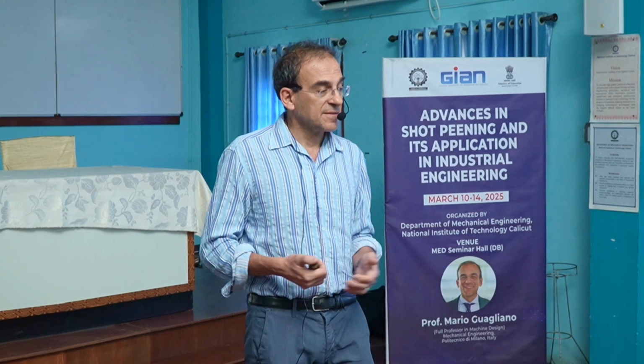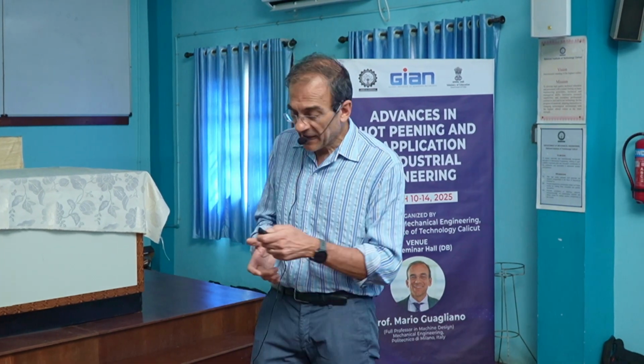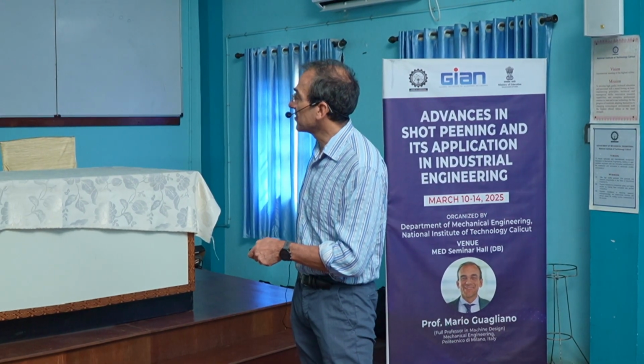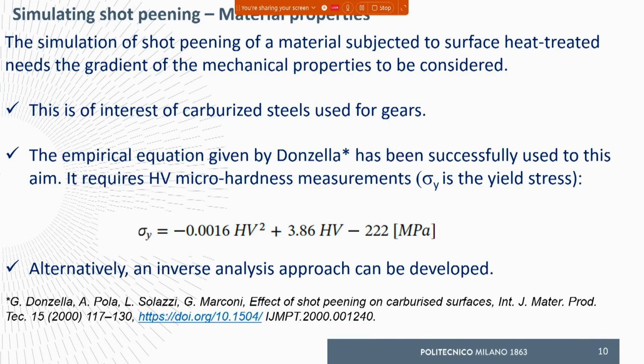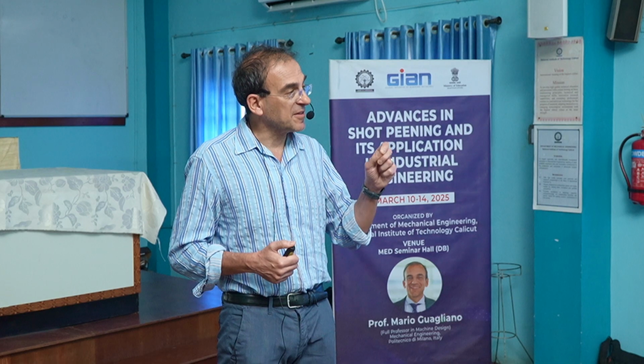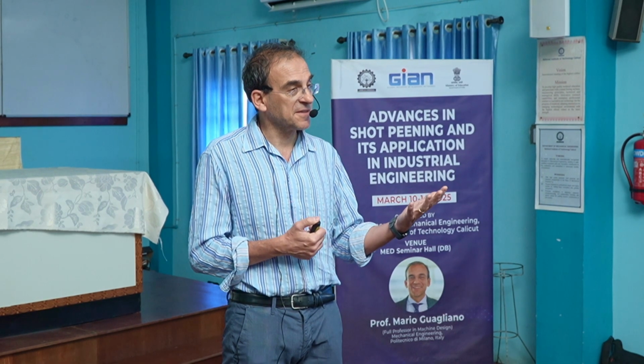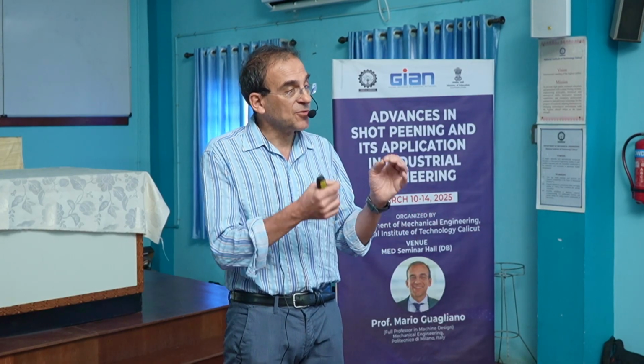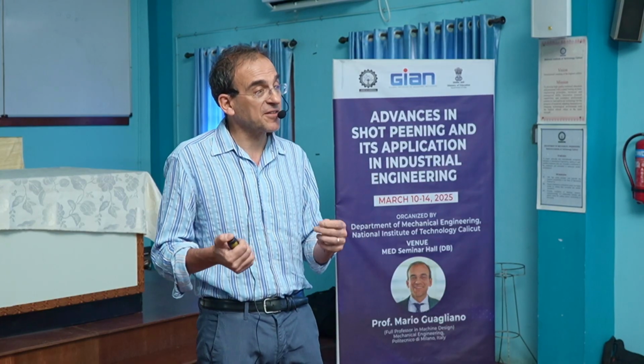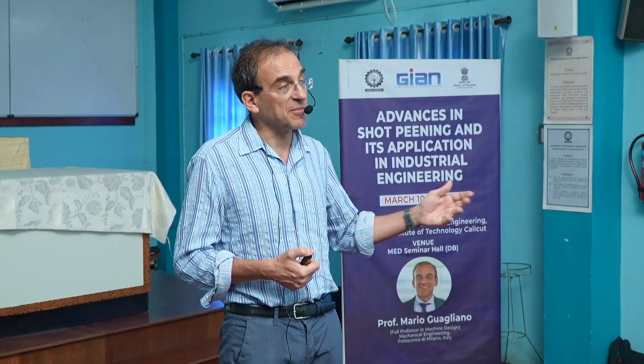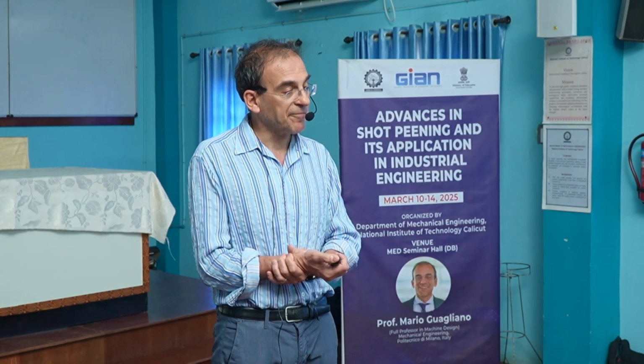Okay. And we also tried an inverse analysis approach, that is to say, by means of simulation and by means of experiment, to tune, let's say, the finite element model parameters in such a way to have the same indentation and the same result of the experimental measurement for hardness.